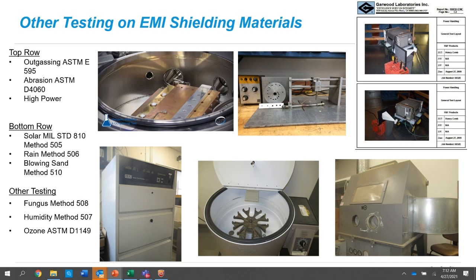The high power test was something pretty unique. These absorbing materials, the way they work is they absorb the energy, electromagnetic energy, and turn it into heat. So normally in most environments, that's okay, that's not an issue. But what happens in certain applications where you're very close to high power antennas, and this could be on, say, a Navy ship or something, that heat up rate can become very important. So a lot of questions revolve around how much heat, how much energy can it withstand? And so we usually talk about that in watts per square inch or watts per square centimeter.